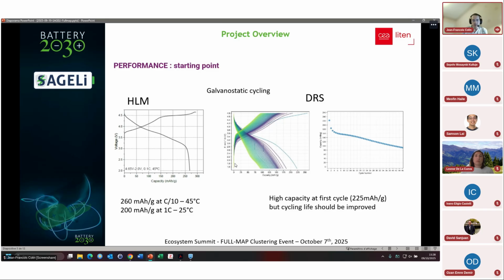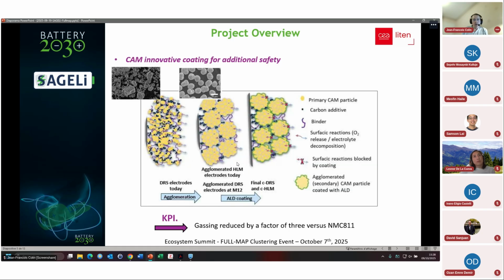Our strategy to stabilize this material is to work on both their morphology and their surface. We know that disordered rock salts have quite a diverse morphology, as you can see, and the idea is to get closer to the classical spherical agglomerates of cathode material. The idea is to have a much better coating if you have a more regular surface, and the coating will be done by ALD to assure a conformal coating and better stability of the interface between the cathode and the electrolyte. So the idea is to reduce by a factor of 3 the gassing of the material at high potential compared to NMC 811, to remove part of the fuel of the thermal runaway.